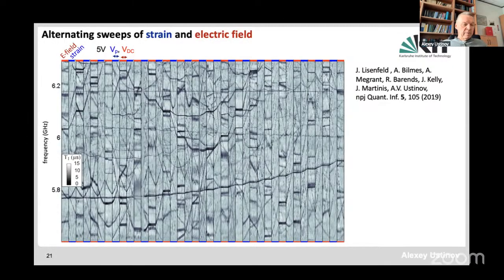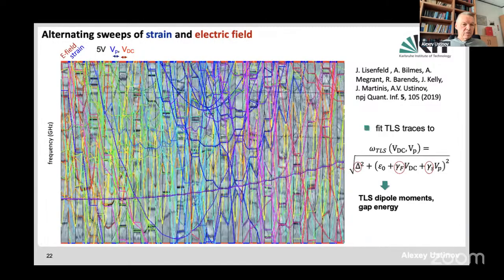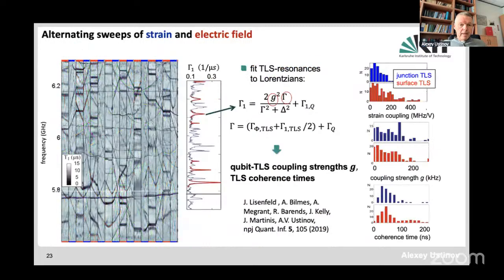And some of them actually react more to field than to strain. By fitting those fragments to all the possible hyperbolas, we are able to extract some statistics of the dependence of the defects on strain and field. And by doing that, we identify the fraction of defects located in the barrier and the fraction of defects located on the surface. And the results of this tedious analysis are shown here.